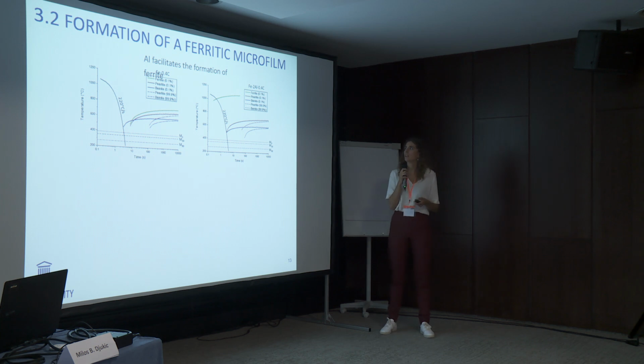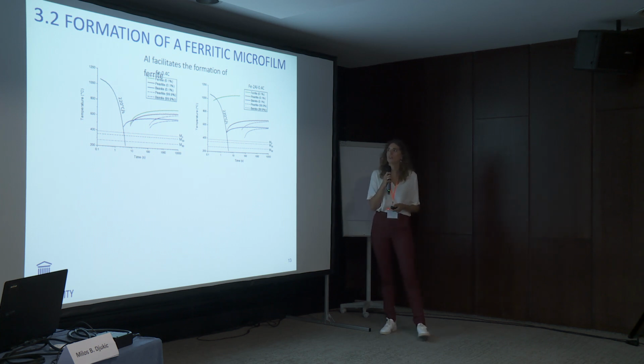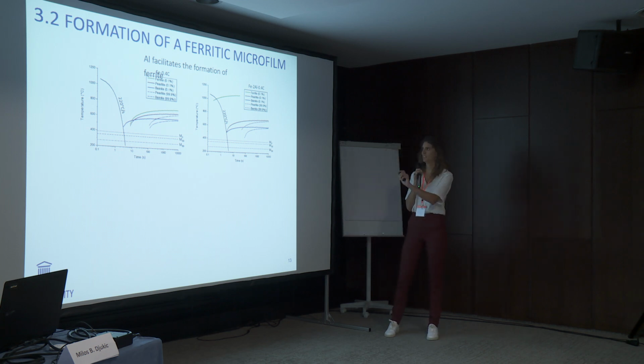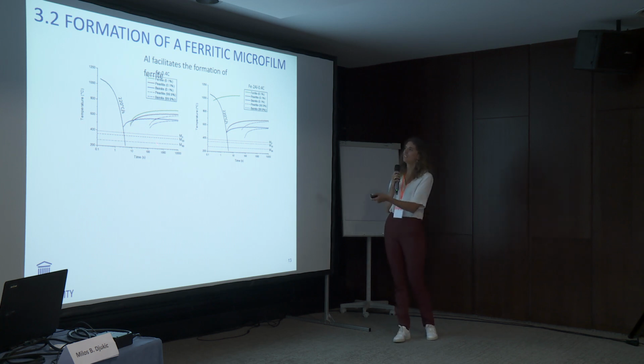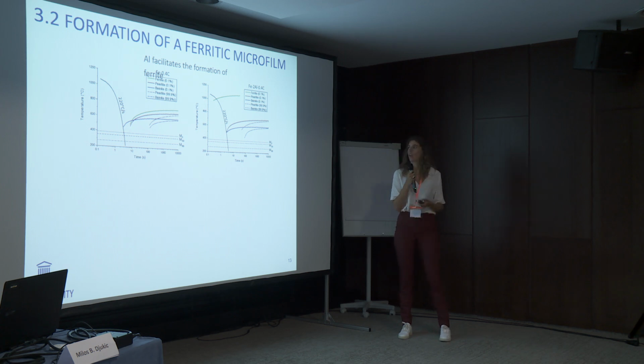How did I do that? Well, by introducing already a very small amount of aluminum, you can really enhance the ferrite formation. There's a bit of shift in the slides I see, but no worries. So this is an example of a 0.4 carbon steel, and by adding already 2 weight percentage of aluminum, we really enhance the ferrite formation kinetics.